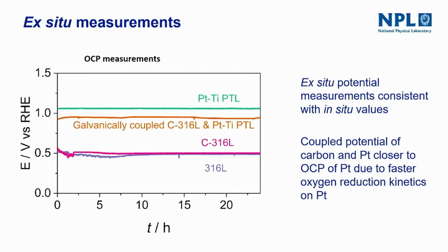Looking at ex situ measurements, just to confirm what the situation is, you have the platinum-coated titanium sitting at just above 1 volt in oxygen. You have the carbon-coated stainless steel and the 316L sitting at about 0.5 volts relative to the hydrogen electrode. And then when you galvanically couple them together ex situ, it tends to sit closer to the potential of the platinum because it's more electrochemically active.